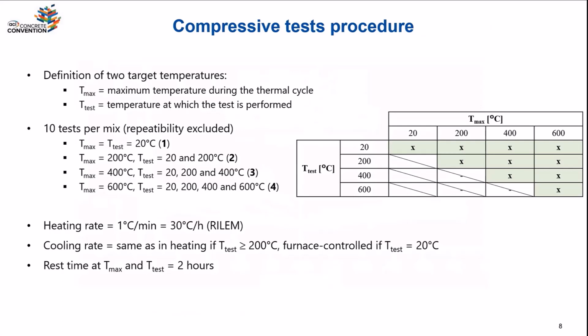So if you look at, for example, the column at the right here in this table, this means that we'll take concrete cylinders, we will heat them to 600 degrees C. Some of them, we will test them at 600 degrees C, so that's the elevated temperature measurement as is usually done. But then others, we will heat to 600 degrees C, wait for a while, cool down to 400 degrees C, wait for the temperature to stabilize, and test at 400 degrees C. We do the same at 200 and at 20, and 20 is the residual strength measurement. So that we track the loss of strength during cooling and the residual value.